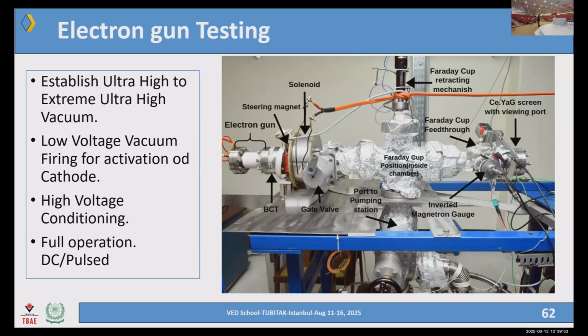So the electron gun is first evacuated from atmospheric pressure down to 10 minus 7 millibars, sometimes 10 minus 6 millibars, and then we have to bake it. Bake the system is the recipe. Bake it to 400 Celsius ideally, but we are limited due to many constraints, because you cannot bake everything at a uniform temperature. You have to be careful, otherwise some brazed joints will just fail. Or if you have viton rings in the system, this will also be a collapse. So you have to bake it gently. We usually go up to 200 Celsius. 120 is the average range where we operate.